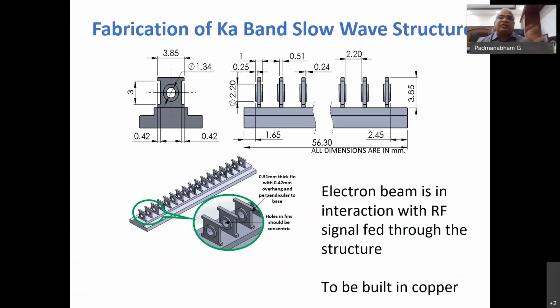Then we had another electronic component. You can see the dimensions here. There are features of about 0.51 millimeters also. And then this is a typical microwave device, a Ka band slow wave structure. I am giving typical examples here. And this is made out of copper. Now, using our SLM machine, this is not possible because it reflects off all the material, all the laser radiation.